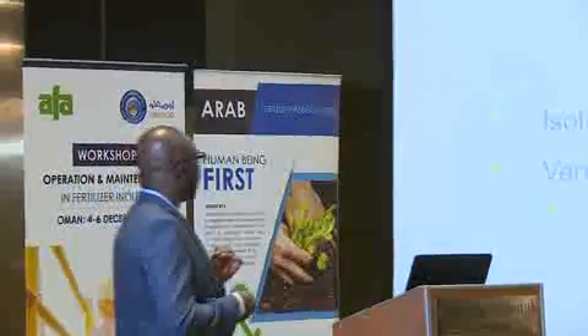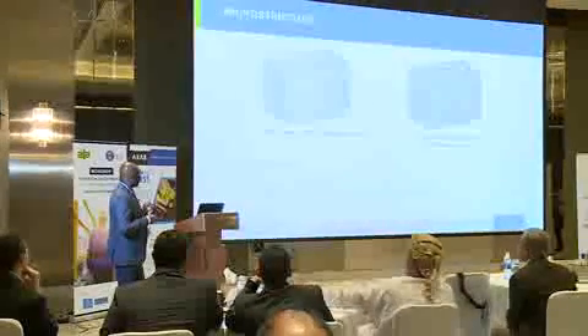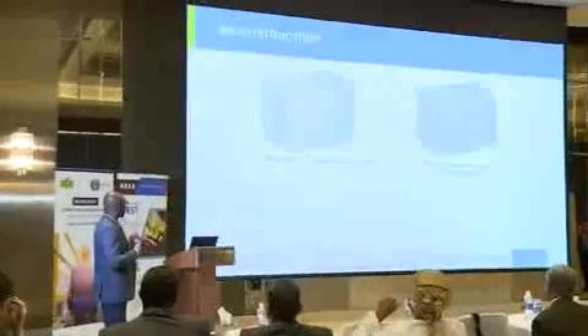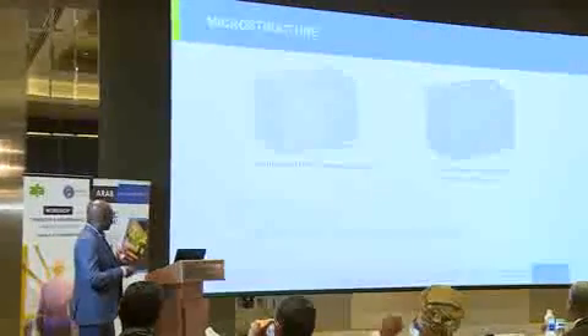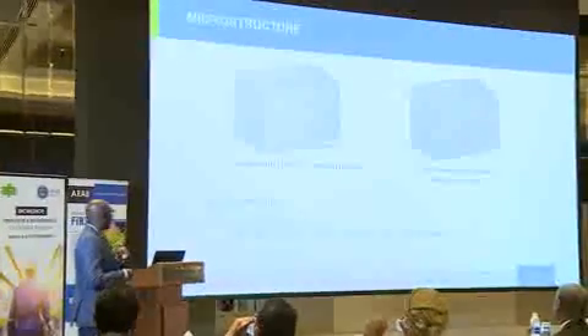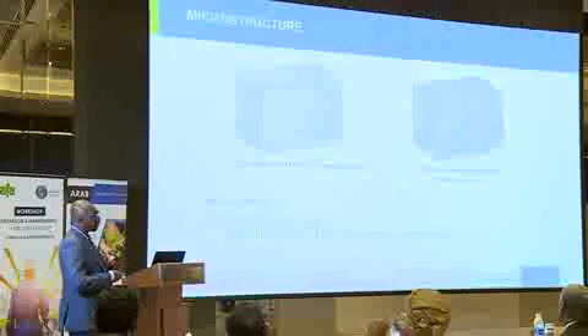And this is exactly what I'm talking about. When you have a hot isostatically pressed structure, because you start from fine powders which are not more than 500 microns big, you end up with a fine structure like this, which is equal in the X, Y, and Z direction. And this compared to a non-isotropically extruded structure.